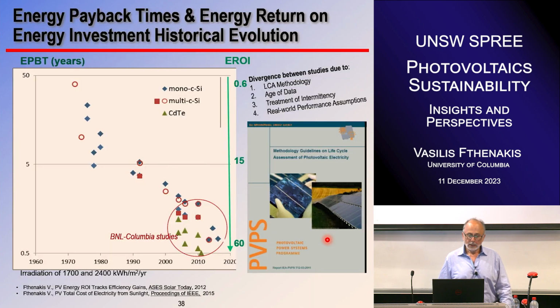Now, energy payback time, as you know, is the time, measured typically in years, that the operating plant takes to produce all the energy that has been consumed in its life, or is going to be consumed at the end of its life. It's still operating. You can see numbers there that go down drastically because early on we had inefficient modules, very low efficiency modules, very thick layers, and perhaps a lot of cemented metals in the foundations.